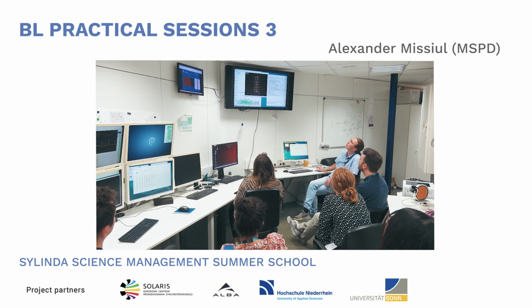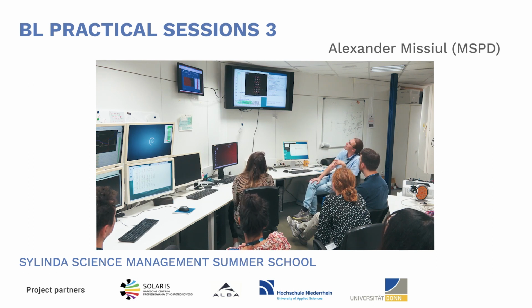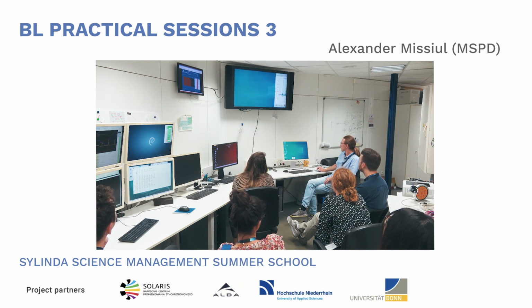And essentially it already stopped because the structure is very simple. For a complex structure, it would take much more time, much more refinement cycles. So normally it might take days until you reach really good models. In our case, it's simple and we are already there. So this is it, and if we compare this with what we had here, essentially it's the same.